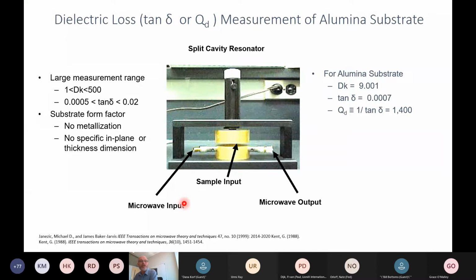But this is a very nice way, a split cavity method. There's a variety of them, split post, split cavity. I'll get into that in the second half of the presentation. In this case, we measured an alumina substrate, permittivity around 9, tan delta very low.